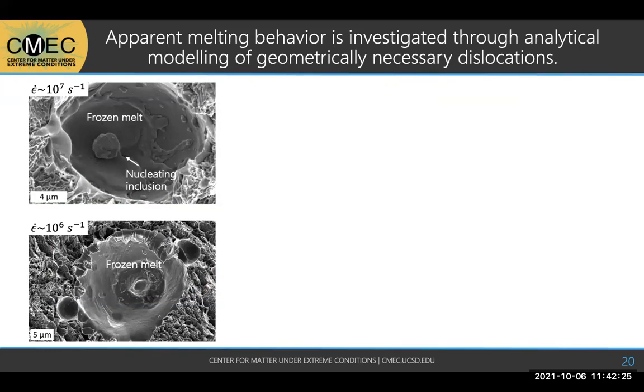So we saw apparent melting behavior, and this was investigated through analytical modeling of geometrically necessary dislocations. This is what I touched on when I said that we calculated the temperature from MD, because in these SEM images, in these really large voids, we see that those inner walls have this characteristic splattering behavior that, to me, says it melted and resolidified. So we wanted to investigate this a little bit further. Next.